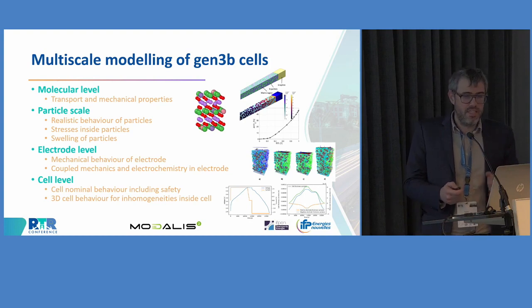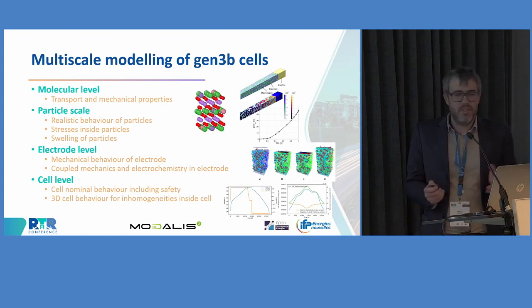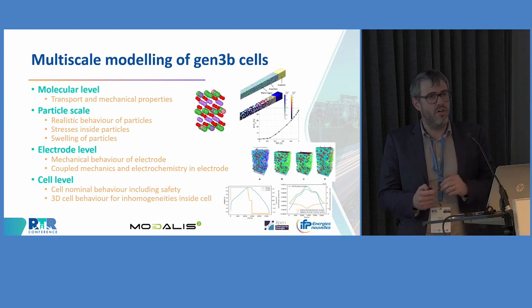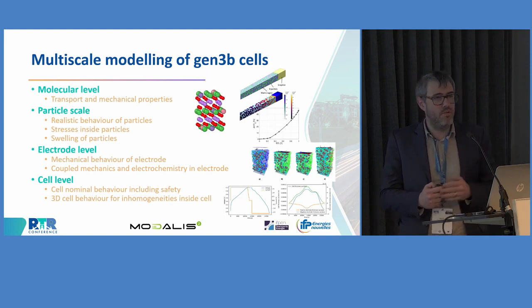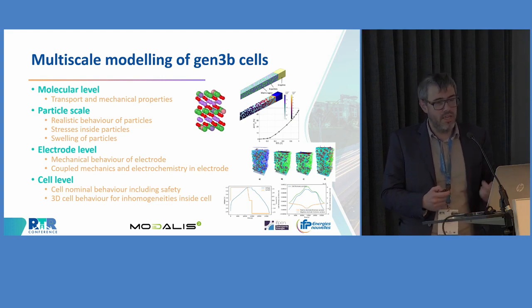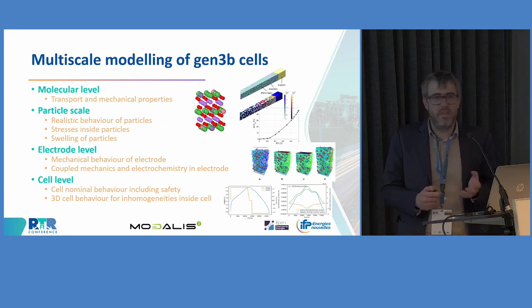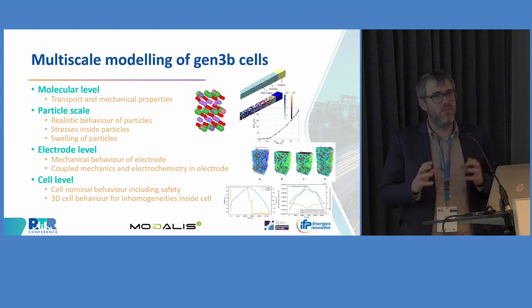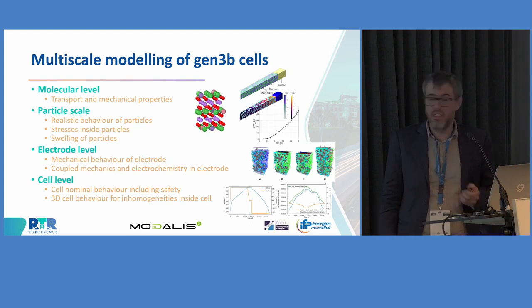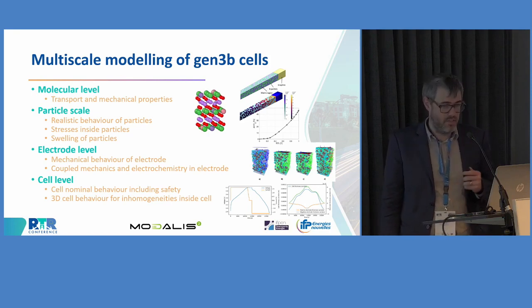So the multi-scale modeling, as I said, was done at multiple scales. First, at the molecular level, we are able to get the transport and mechanical properties of the materials, especially for the NMCs, the diffusion parameters of the NMC, and the mechanical properties of the silicon. Because as we bought some commercial material with silicon coupled with graphite, it was not possible for us to separate silicon and graphite and analyze them separately. So we had to guess the material behavior from DFT calculations.